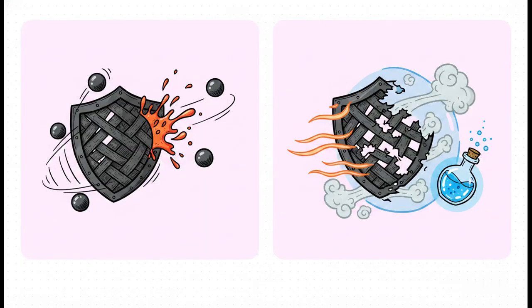But there's a strict trade-off happening here. Carbon's armor is perfect in many ways. It repels basic slags, provides extreme toughness, and conducts heat brilliantly to prevent that thermal shock. However, carbon's weakness is oxygen. Above 600 degrees Celsius in regular air, the graphite literally oxidizes. It burns away into carbon monoxide and dioxide gas, leaving the brick totally porous and weak. And that is exactly why we must carefully add chemical antioxidants, like silicon carbide, to protect the armor itself.